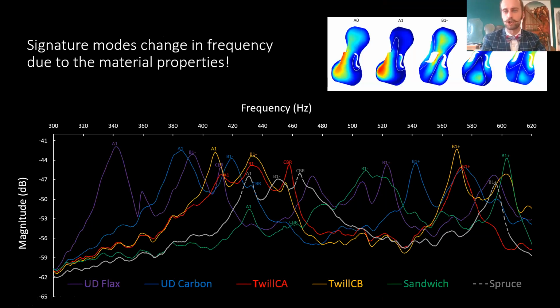So then you see the signature modes, and they change in frequency due to the material properties. So that's already a good sign that we're measuring the material properties, we change them, and we can see it in the measurement. Here at the top, you can see the modes. And here we have the A1 mode. We're not really sure if we should call it the A1 mode, because actually here you see that it changes a lot in frequency. And the A1 mode should be an air mode mostly, but that's for a detailed discussion, which maybe we can have after the talk. But you see here, for example, this is just a signature mode. So the A0 is below here.